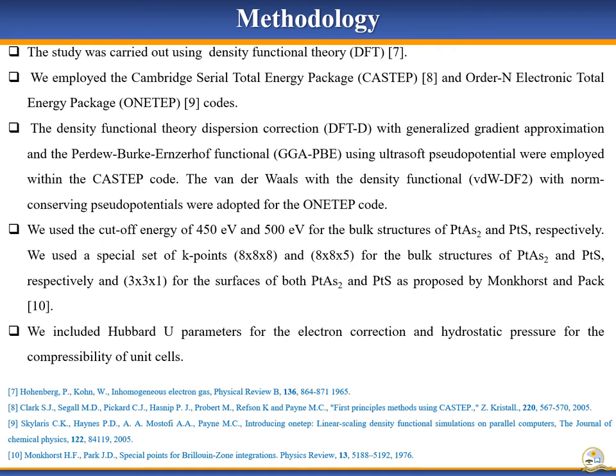For CASTEP, we utilized density-functional theory with dispersion correction using ultra-soft pseudopotential. For ONETEP, we utilized NGWFs using norm-conserving pseudopotential. We used cutoff energies of 450 eV and 500 eV for the bulk structures of sperrylite and cooperite respectively. We then used K-point sets of 8×8×8 and 8×8×5 for bulk structures of sperrylite and cooperite respectively.